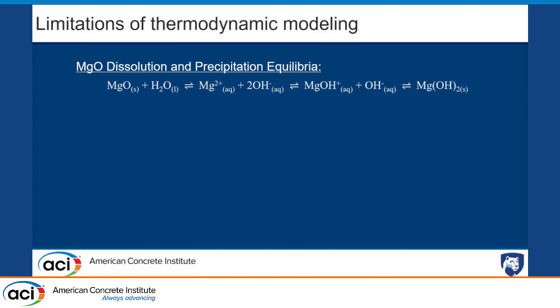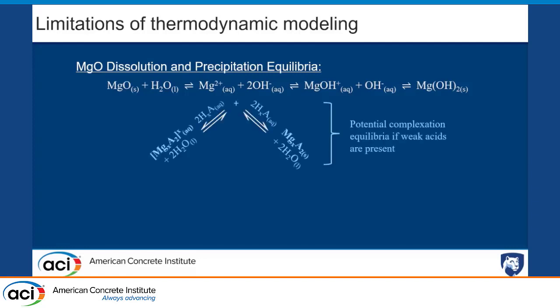What we just saw. Now, what happens is that we can actually add these organic acids, which lower the pH because they're an acid, right? But they do something really, really cool. They can actually create complexation for the magnesium ions that we're seeing here. So they can complex with the magnesium ion, right? Create what we call ligands, and take them away from the surface that is dissolving for that magnesia, right?